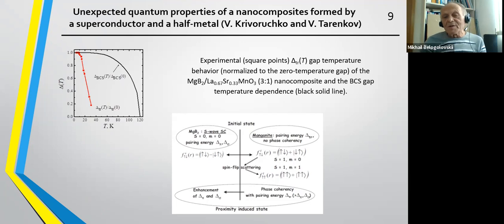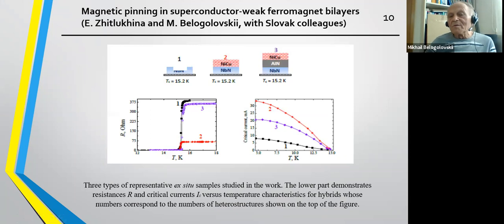So the explanation of the authors, or rather hypothesis, I would say, is that really in the manganite there is already local superconductivity, but there is no global superconductivity. And this superconductivity should be, of course, of spin triplet origin, otherwise it cannot be in such material. But the proximity to magnesium diboride in these samples helps the manganite to create a global superconducting ordering. So it should be checked more, and of course, new experiments should be done with these materials that can be provided by my colleagues.